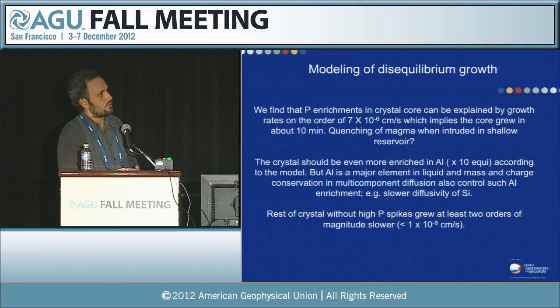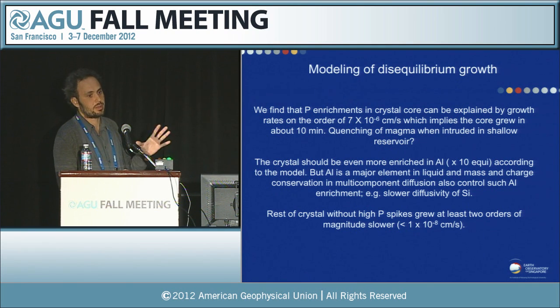Okay, so, partial conclusions: this phosphorus enrichment requires these types of growth rates, and basically it means that this core grew in 10 minutes. So I think this is showing that there was a quenching. You have the magma, it's hot, it moves from the deep part to the upper reservoir, and then it quenches and you grow these high phosphorus zones.